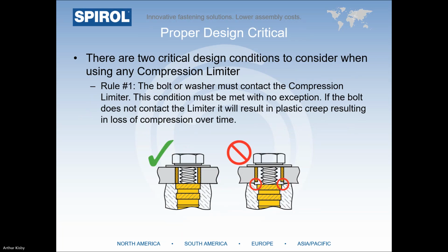There are two critical design rules to consider when using any compression limiter. Rule number one is that the bolt or washer must contact the compression limiter. This condition must be met without exception. If the bolt does not contact the limiter, it will result in plastic creep and ultimately loss of compression over time. The image on the right would not be acceptable if the bolt was fully torqued down.